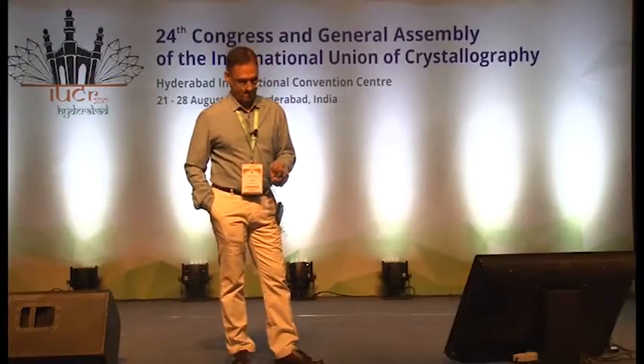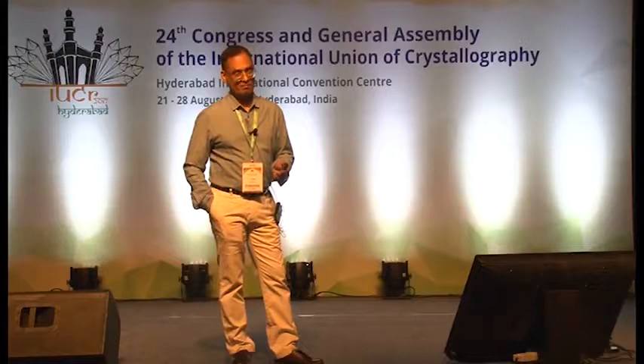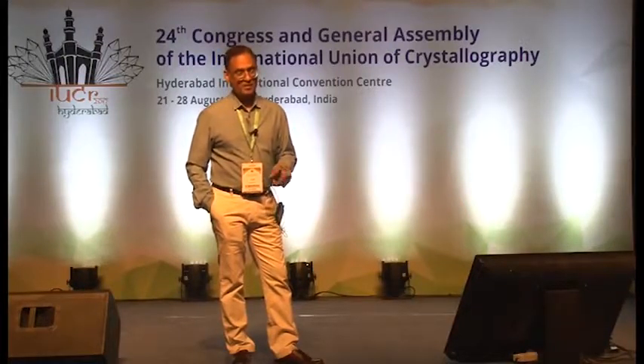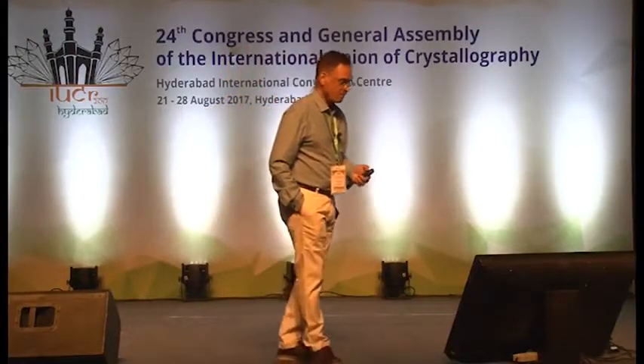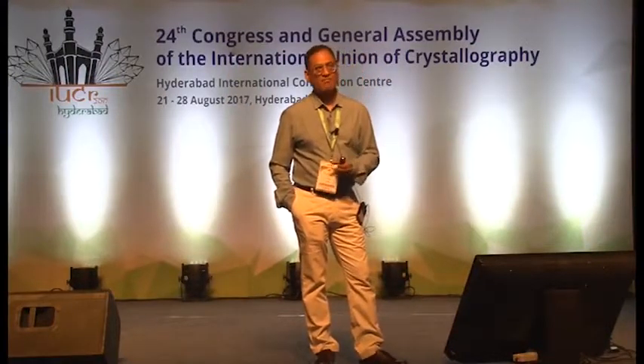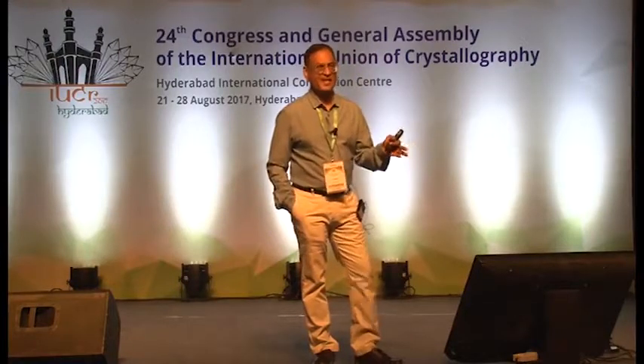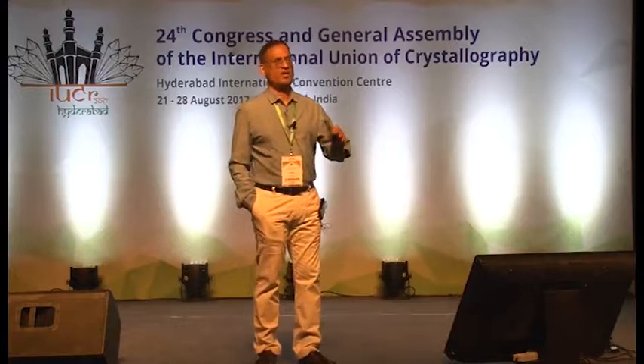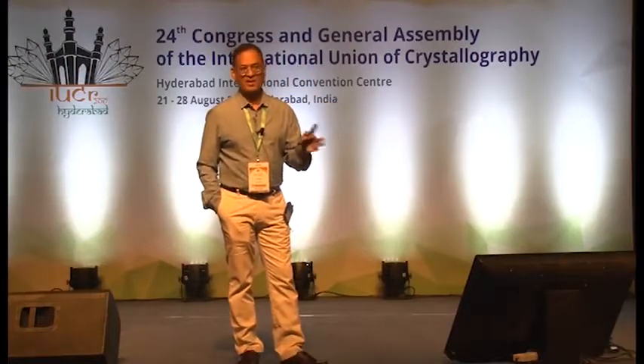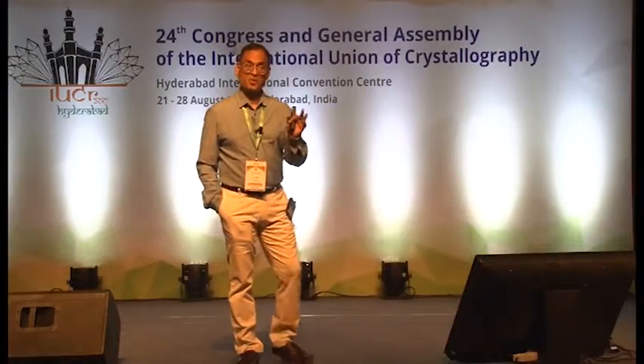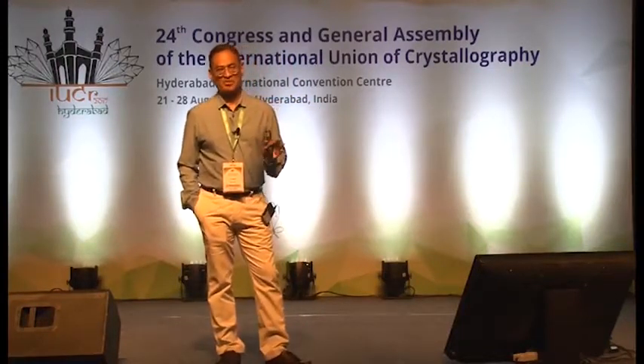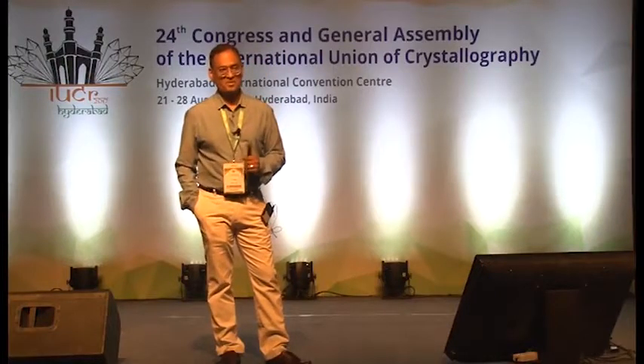Okay. Just for a comment, in photoluminescence studies, what I've seen in the literature now, they are heavily looking into the solvent interactions with the prime molecules and how the interaction mode between the prime scaffold and the solvent influences the whole photoluminescence. Yeah, maybe, but you can look in that direction. Yeah, but in this case, they're all disordered, highly disordered. We got this information only from NMR, TG, mass spec, and IR and everything. So if there is no disorder, then we can look for hydrogen bonding. Then we'll get more insight into this type of problems. So far, we don't have.